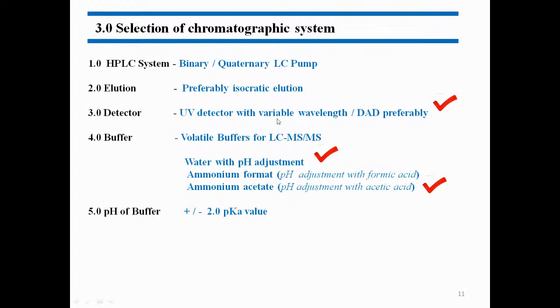Buffers: definitely for characterization, you need to shift your method from HPLC to LC-MS. So you require a volatile buffer, because you know that your ion should be in a gaseous state when you analyze by LC-MS. So you need a volatile buffer so that it does not deposit any salt material. If I take potassium hydrogen phosphate, which is not a volatile buffer, then I will get a lot of salt deposit in my MS system, and the performance of the MS system will not be good if we use a non-volatile buffer. So the most frequently used buffers for LC-MS systems are ammonium formate and ammonium acetate. You can adjust ammonium formate buffer pH using formic acid, and ammonium acetate you can adjust with acetic acid.